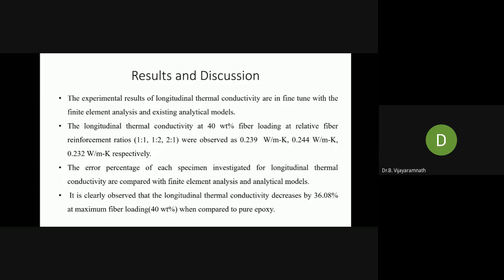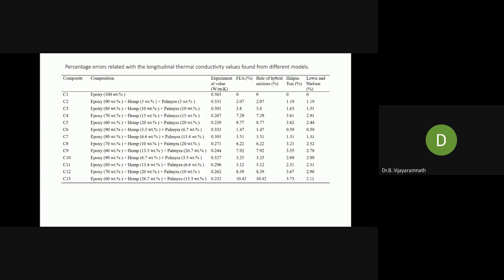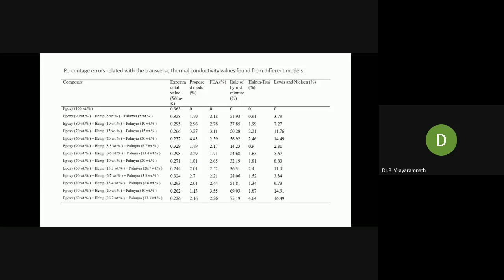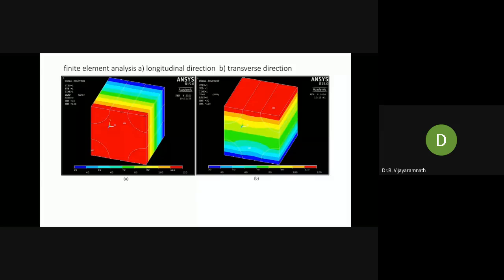Similarly, the FEA model results we can see here. The first FEA diagram represents the longitudinal direction, the other one is the transverse direction. Rather than at the edge of the specimen or the laminate, the mid part of the laminate is providing a good result. That's why FEA is very much in line with the experimental results as well as the mathematical models we have generated.